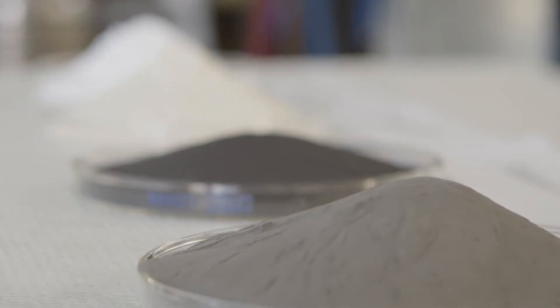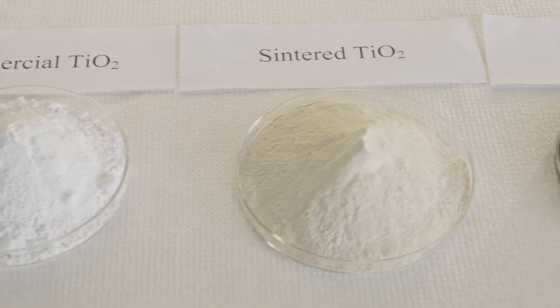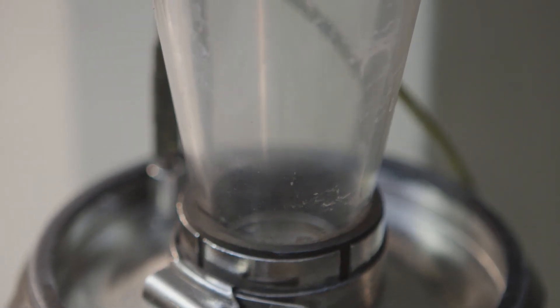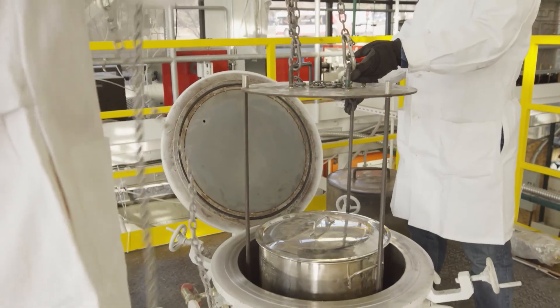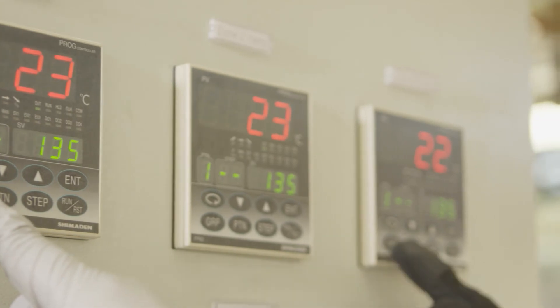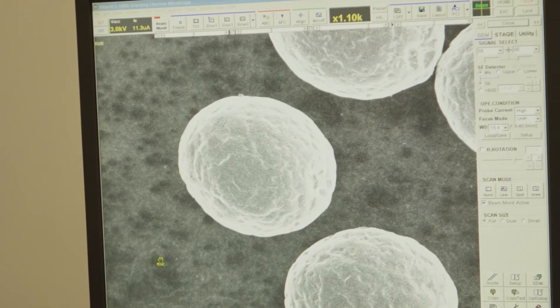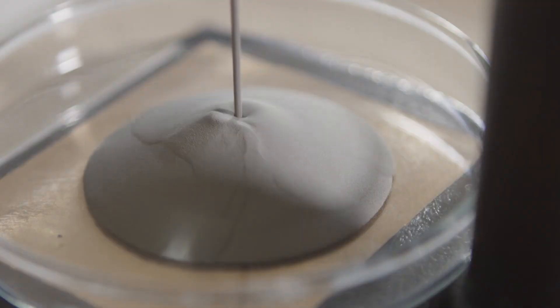Titanium is one of the metals we focus on because it is a great metal — sometimes referred to as the metal of the future, though I would like to see it as the metal of the present. We take a feedstock material, titanium dioxide, which is a low-cost commodity, and blend it with magnesium metal powder. We put this blend in a crucible, place it in a reactor in the furnace, heat it up to about 700–800 degrees C, cool it down, and end up with the titanium hydride we're looking for. We also develop a process using the same approach to make a spherical titanium alloy powder that can be used for 3D printing.